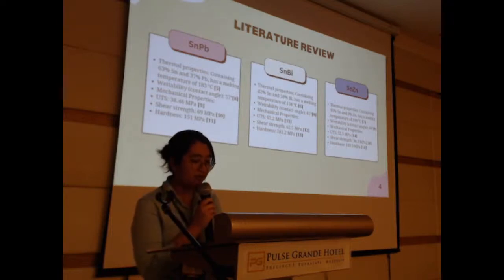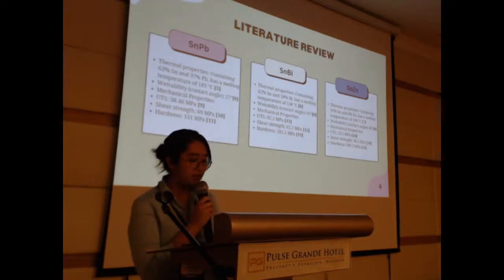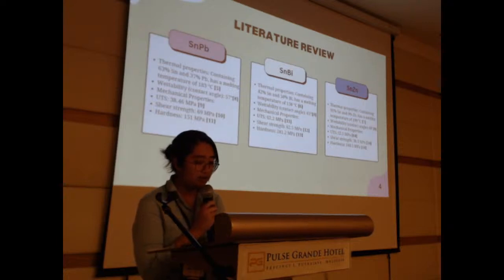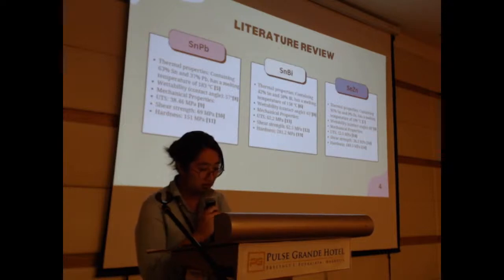lead and also bismuth, bismuth has the best properties, where the melting temperature is lower than lead, and the mechanical property shows higher values. Comparing bismuth and zinc, which is another lead-free solder, once again bismuth shows the lower melting temperature compared to zinc, and the mechanical properties of bismuth show better values than zinc.